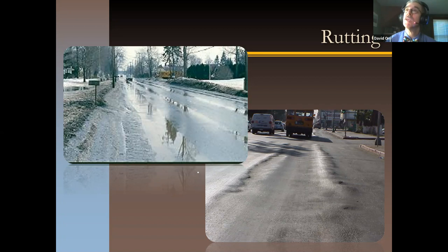Okay? Now, somebody put into the Q&A pod, are you assuming the pavement surface is milled first? You could do that. You could mill it flat, and then you'd have a nice foundation, just like a gravel foundation, to pave on top of. And that actually is a really good technique, a mill and fill type operation to get a flat surface. But that assumes the mix is stable. If the mix is moving, as in the lower right photograph, you could mill that flat, but that underlying mix is probably still unstable and it's going to move with traffic. So make sure you understand what's going to happen. Pick good candidates before you do the overlay, okay?